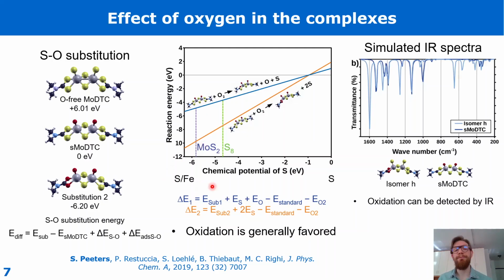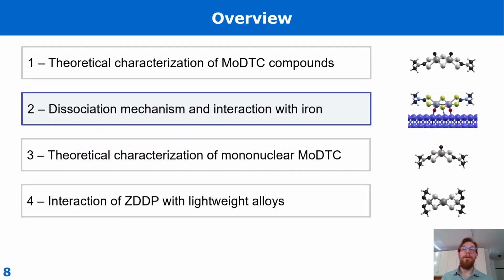But we also considered vibrational spectra of these additives, and actually they are all very similar to each other. But we can find some diagnostic peaks, for example the molybdenum double bond oxygen stretching, which is found at 1000 centimeters to the -1. And this kind of simulation can be very helpful to ease the experimental characterization of these compounds. So now I'm going to discuss the dissociation mechanism of MoDTC on iron.